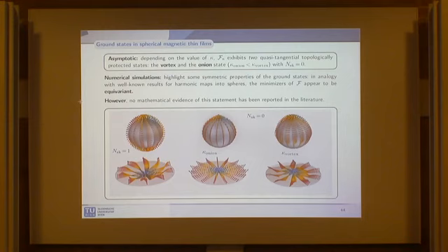If you, for example, look at this transformation from the sphere to this disk, and write the energy as a 2D energy, now defined on this disk, then even if you don't have any DMI, what appears is this kind of curl m dot m term, which seems to be created by the change of coordinates.